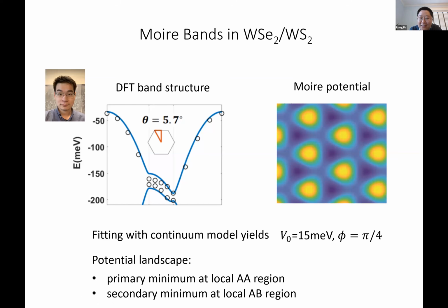of the potential. But here, interestingly, there are two types of potential minimums. The primary minimum is located in the AA stacking region, local AA stacking region, and the secondary minimum is located in the local AB stacking region. So in this figure, the primary minimum is here, it is the dark spot, and the second potential minimum is here.